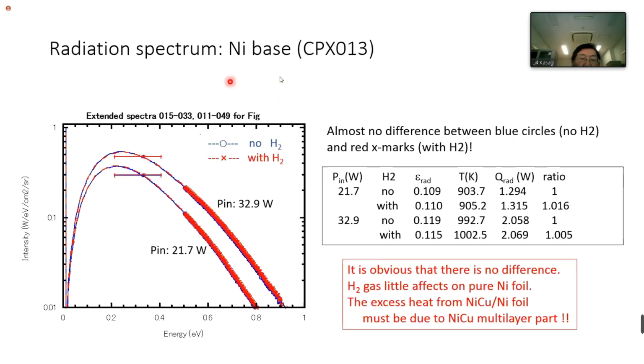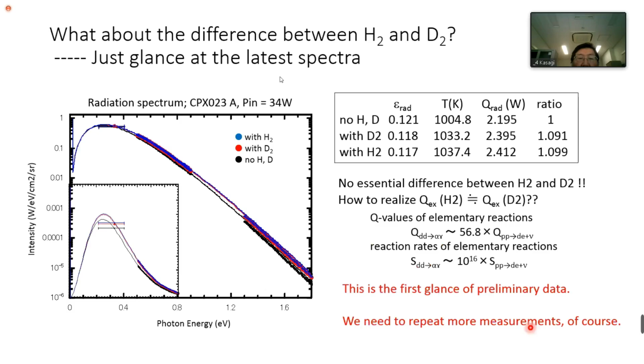So this is a radiation spectrum from the nickel base itself. It is obvious that there's no difference. The hydrogen gas has little effect on pure nickel foil. The excess heat from the combined foil, I mean, nickel-copper based on nickel foil, must be due to the nickel-copper multilayer part. And then finally, what about the difference between H2 and D2?